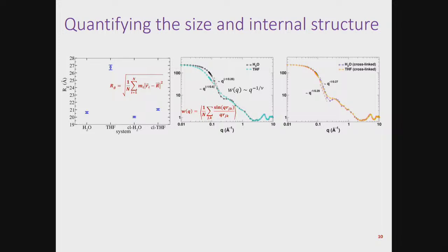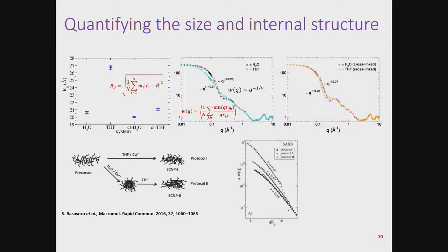So it means that the polymer is retaining its internal architecture and it is swelling when you transfer it to THF from water. This is an important application when we think of drug delivery. You can prepare this polymer in water and load the drug and transfer it into a better solvent, which is THF, and in that process it swells and releases the drug. This is just a potentiality that we are expecting with this output.